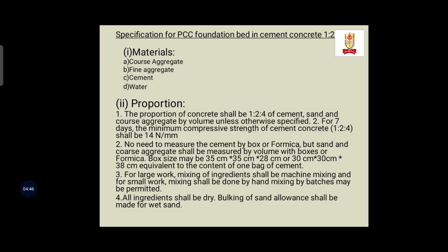Now the second one is proportion. The proportion of concrete shall be 1:2:4 of cement, sand and coarse aggregate by volume unless otherwise specified. For 7 days, the minimum compressive strength of cement concrete 1:2:4 shall be 14 Newton per mm square. There is no need to measure the cement by box, but sand and coarse aggregate shall be measured by volume with boxes. Box size may be 35 cm into 35 cm into 28 cm or 30 cm into 30 cm into 38 cm, equivalent to the content of one bag of cement.